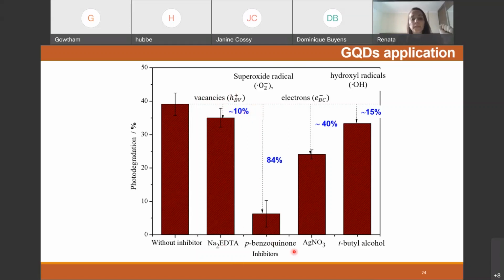In the presence of parabenzoquinone, which inhibits the superoxide radicals, it is possible to observe about 80% inhibition. And in the presence of silver nitrate, which inhibits the electrons, it is possible to observe about 40% inhibition.